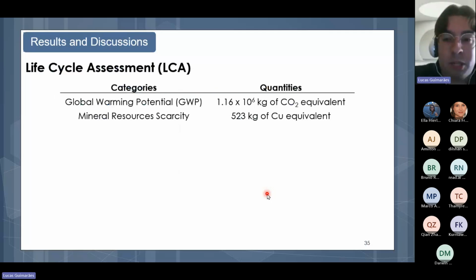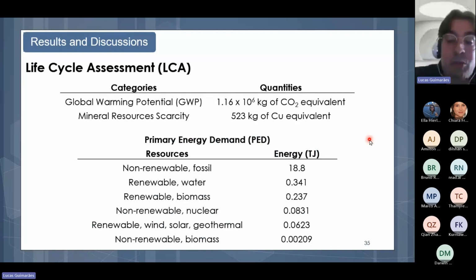The results for the LCA found in SimaPro considered the base scenario of a linear scale up from the laboratory scale to a scale in which we could produce 1 ton of lithium hydroxide. The quantity found for global warming potential was 1.16 times 10 to the 6 kilograms of CO2 equivalent. And for mineral resource scarcity, the quantity generated according to SimaPro was 523 kilograms of copper equivalent. And for primary energy demand, the results show that the most used energy was a non-renewable, fossil one, with a value of almost 19 terajoules.